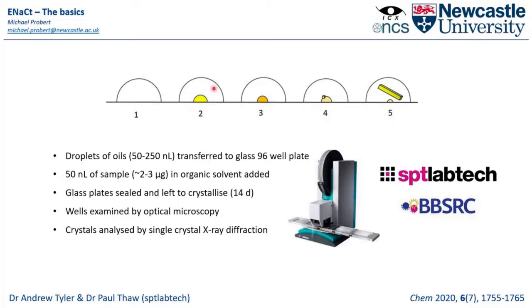So we get our initial injection, our concentration with either concentration by diffusion or evaporation with solvent leaching along the border between the oil and our glass slide, leading to a nucleation and then crystal growth that we could then extract and run single crystal X-ray diffraction analysis on.